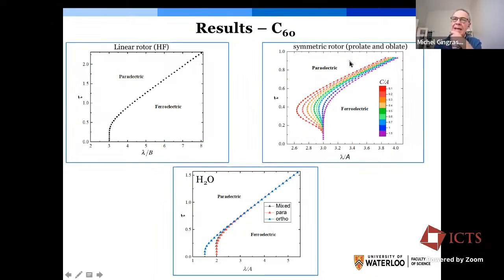The symmetric rotor corresponds to a molecule that would be akin to a prolate or an oblate, a pancake-type molecule. So for example, ammonia would be a realization of a symmetric rotor. Ammonia can be inserted in C60. There is again a ferroelectric phase and a paraelectric phase, but what's interesting in this case is that depending on the aspect ratio, the ratio of the rotational constants, one can have an interesting reentrance phenomenon. For example, if the molecules tend to be oblate-like, that is pancake-like, there is an insertion of the ferroelectric phase above the quantum disordered phase.